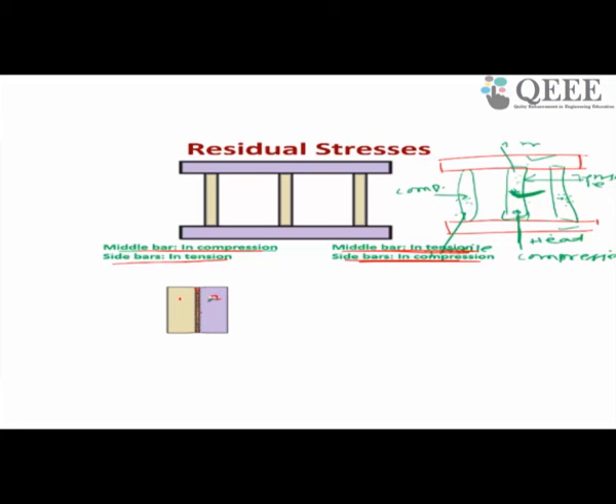However, when you cool after welding, what will happen? This zone will cool. During cooling, it will try to contract. So a tensile stress field will be generated in the weld pool, and this will be resisted by the side base material. So a tensile stress field will be developed in the weld and a compressive stress field will be developed in the base material. As a result, in welding, suppose this is your axis, you will get something like this. Suppose I draw it on a bigger scale.